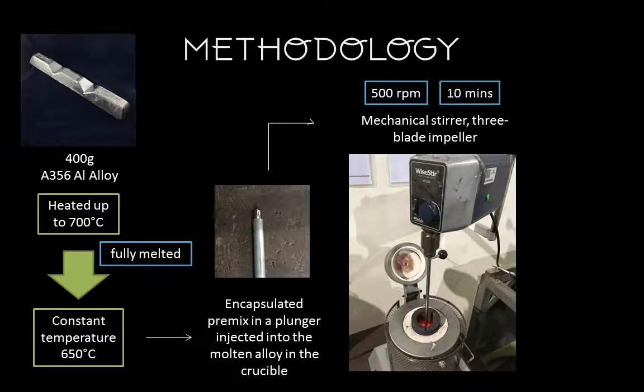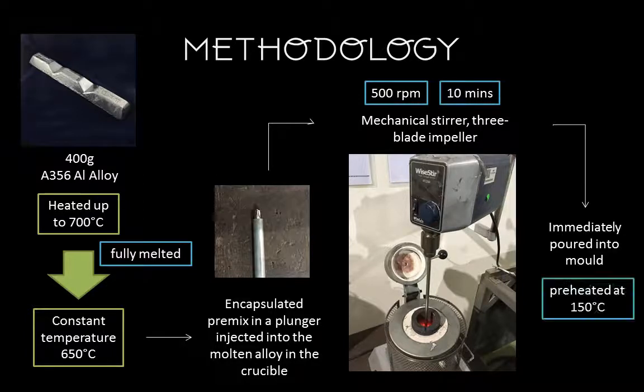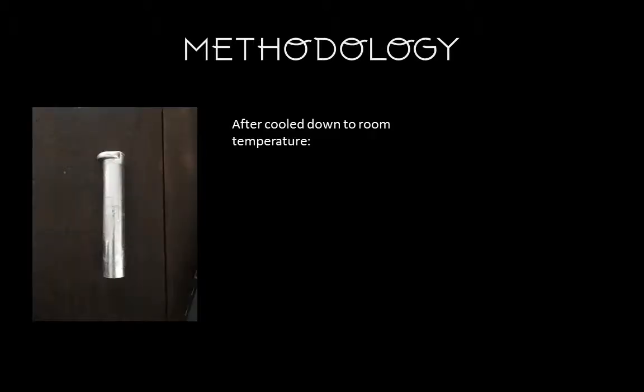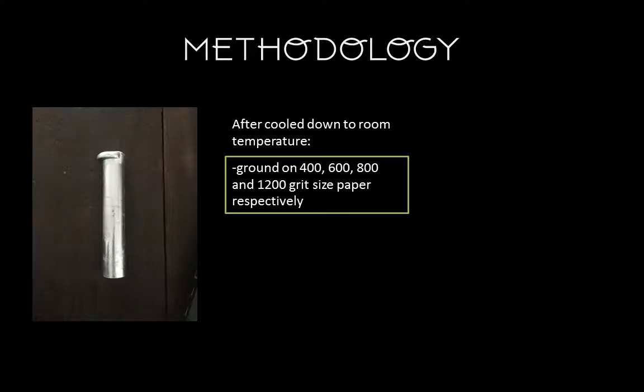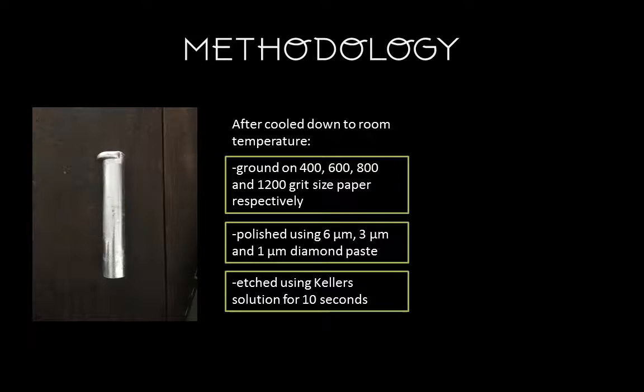After 10 minutes, it will be immediately poured into a mold which is preheated at 150 degrees Celsius. Next is to prepare the sample. After it is cooled down to room temperature, it will be ground, polished, and etched using Keller's solution for 10 seconds so that it can be observed under the optical microscope.